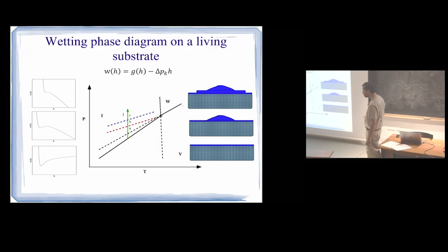The system likes to go to infinite thickness. And that's exactly the way free energies look when you get liquid droplets. You have a region where the pre-melting film is metastable and can be stabilized, but water wants to condense in the form of a droplet and keep growing as a big droplet. And that occurs exactly at this line.